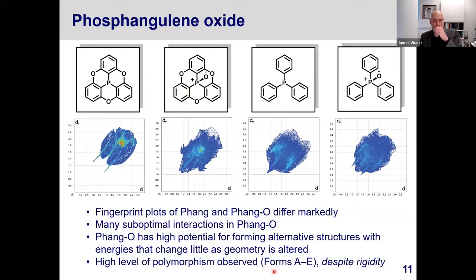And in our work, we characterized 5 different forms without really going after the full screening of the different polymorphic forms. It was a relatively straightforward search. Elise would come to me and say, Jim, I've just found another polymorph of phosphangulene oxide. And I would say, well, why are you doing this? I mean, we have other things to do with this phosphangulene and phosphangulene oxide. But she insisted, and she insisted correctly. And ultimately, we came up with 5. I think there are more that could be found if we look for them. The interesting thing is that this is a compound that's highly polymorphic.